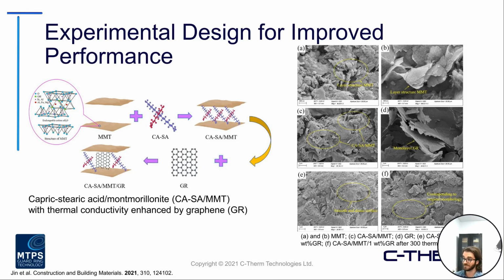What was really interesting is that in the image to the right, after 300 thermal cycles, the morphology remained fairly constant. So when it went through that melt to solidification cycle 300 times, it still maintained its form quite well, really lending itself to good thermal cyclability.